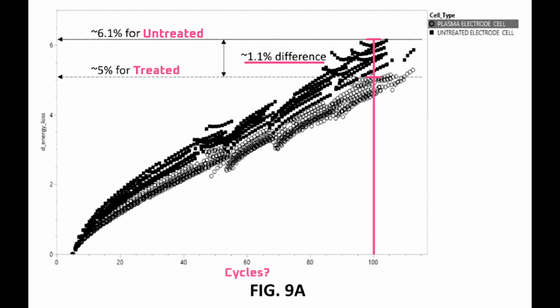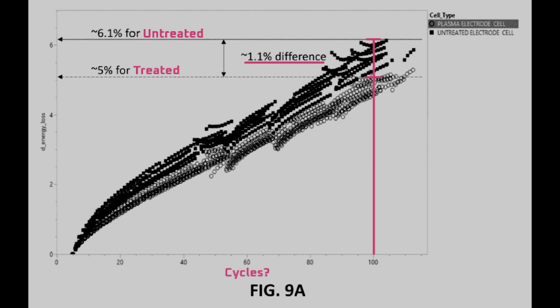Figure 9a shows that the plasma-treated battery cells also retained more energy on cycling tests than the untreated. It appears that around 100 cycles, the plasma-treated electrode retained 1.1% more energy than the untreated electrode. Again, I'd be interested to see how the dry-coated plasma-treated cell compares to a conventionally produced cell.